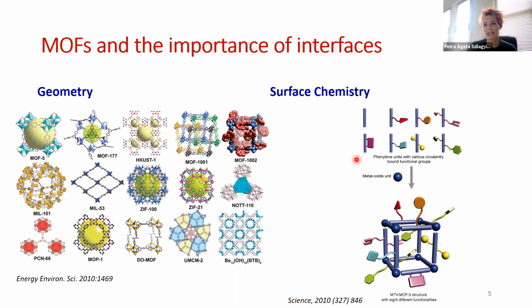And the other aspect we are looking at is the surface chemistry. So particularly the organic part, but not exclusively, may bear all sorts of different functional groups in the framework. As we're using it as a template and also as a host for guest clusters, these functional groups may interact to different extents, with different strengths, with the guest material. So we can tune this kind of host-guest chemistry by selecting these different functional groups, and thereby, so our hypothesis goes, we can fine tune a little bit the surface electron density